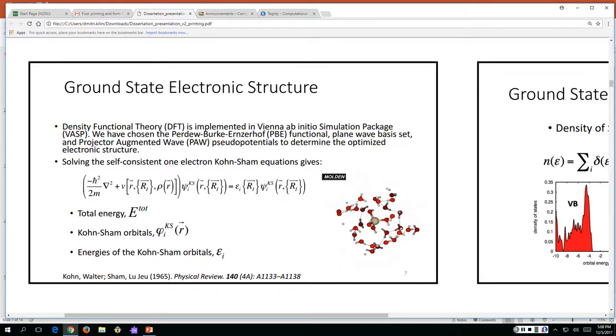Also noted is the fact that we hadn't used spin orbit coupling corrections, which are necessary in these types of materials. And so, to try and appease some of the reviewers, we worked in calculating the absorption spectra with spin orbit coupling. And so for the systems, you can see that the spectra themselves don't change much in shape. The majority of the change occurs only in energy shifts. And so when looking at other types of calculations done for spin orbit coupling, we know that different bands at the bottom of the conduction band are going to split, reducing the energy of one instead of having a degeneracy. And so this is one of the things that is a primary contributor to this shift in energy.